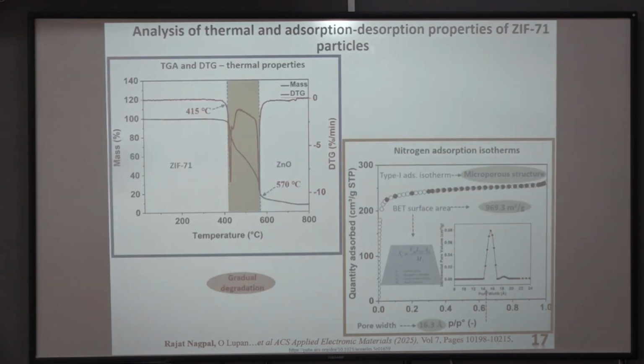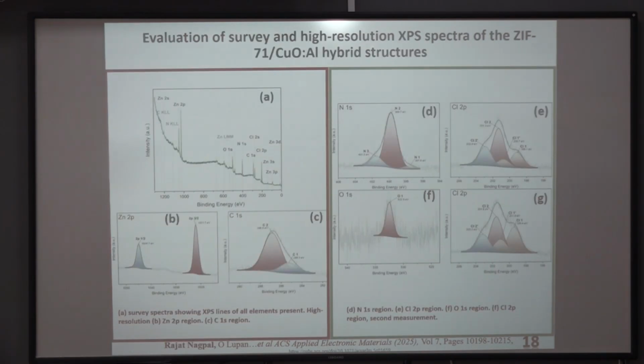Now to get insights about the ZIF-71 hybrids for thermogravimetric analysis, here we can see going from room temperature to 415 degrees Celsius, it retains its structural framework, and then there is gradual degradation, and at high temperature, its transformation into zinc oxide. To get more insights about adsorption isotherms for the ZIF-71 hybrids, here we can see even at very low nitrogen pressure, there is quick nitrogen uptake and then a stable plateau, which confirms its microporous structure, and BET surface area was calculated using this equation.